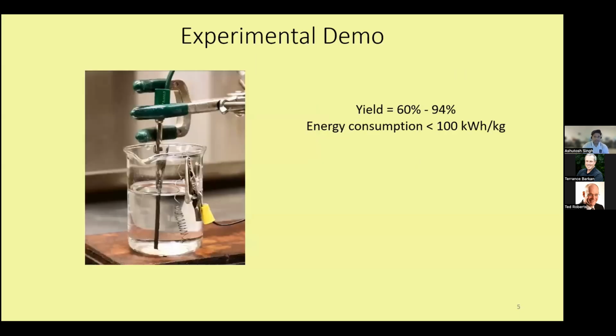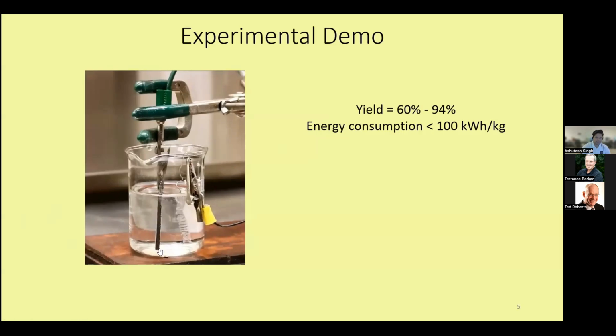What I have here is a video demonstration of how this process works, just to quench the scientific thirst of many scientific members in the audience. It's a school-type demo that I want to play for everyone and explain the process. As we start the electrochemical process, if you carefully observe the graphite foil, you can see its width gradually increasing from its initial thickness. This stage is what we call intercalation. After a while, as the exfoliation propagates, you can see that the water associated with salt ions inside the layers starts to convert into oxygen molecules, creating a pressure between the layers and pulling them apart.